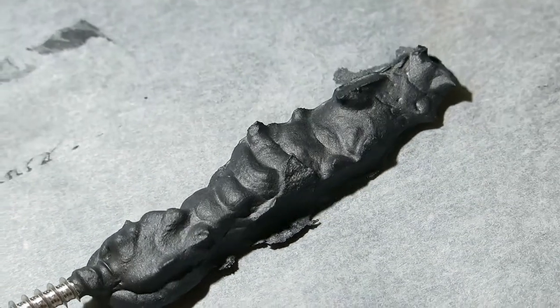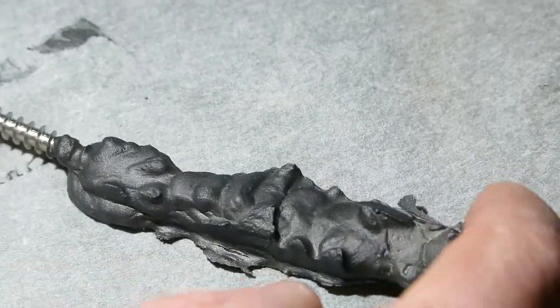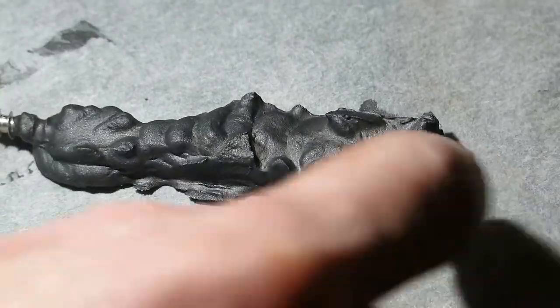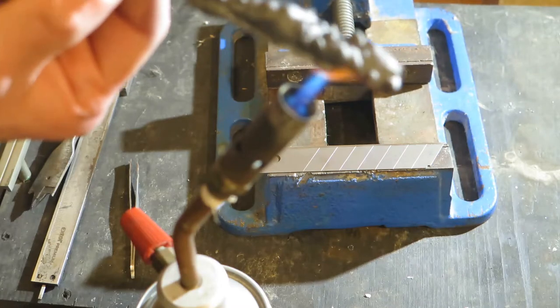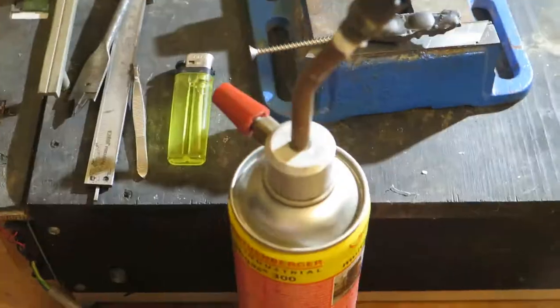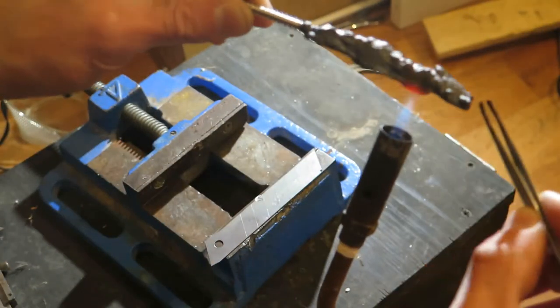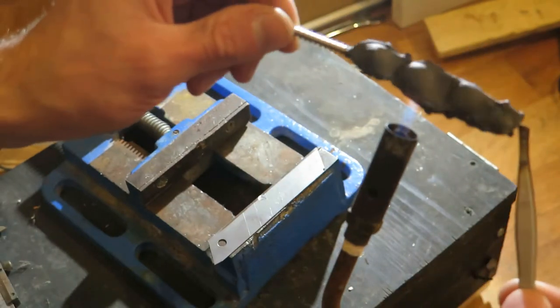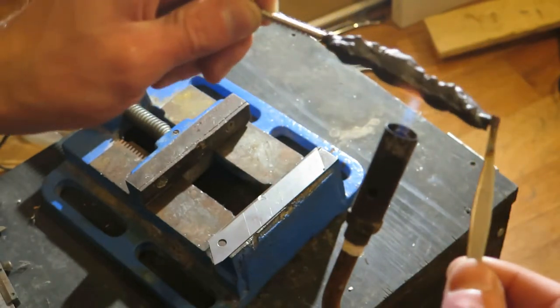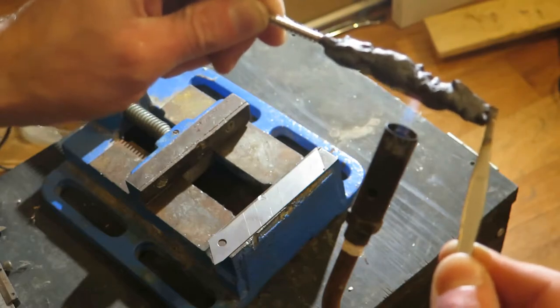After some slow drying it looks like this. It is a good idea to slowly ramp up the temperature until all water is gone, otherwise the vapor will deform the shape of the tool. Then by heat treating the tool it will become insoluble in water. According to the article that I read, the required temperature seems to be about 400 degrees Celsius.